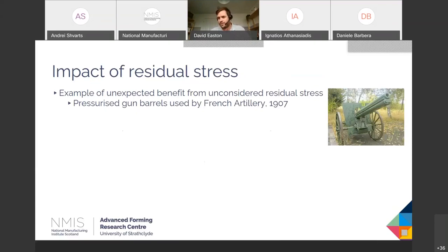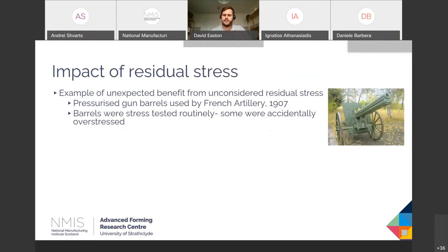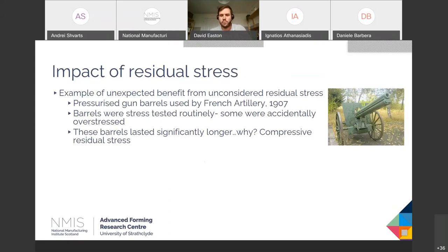Back in the early 1900s, the French artillery would manufacture gun barrels. Part of their routine manufacturing process was to stress test. So they'd apply a given stress level, apply a hydrostatic pressure, and if the parts passed, then they'd go into service. Well, what happened in this case is some of them were accidentally overstressed to a much higher pressure than intended. Rather than scrap these parts, they thought, well, they're fine, we'll put them in service and see what happens. And in actual fact, these parts perform better than the standard barrels.